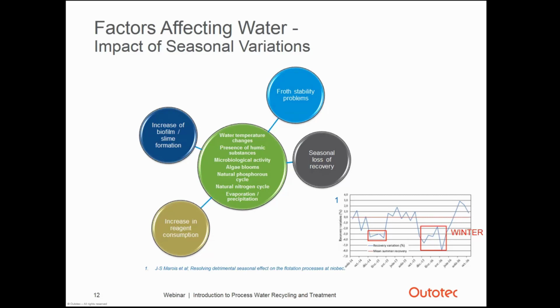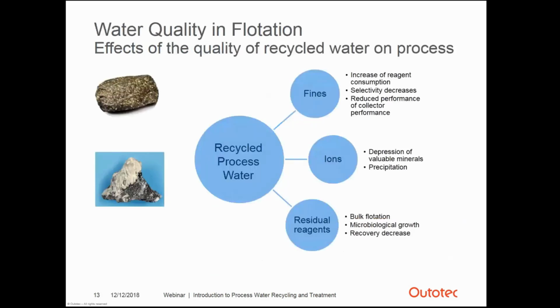There are several components that can be accumulated in recycled process water and therefore harm the flotation performance. Here are the most critical ones: fines, ions, and residual reagents presented in these blue bubbles. Firstly, fines. And when we are talking about fines, we consider under 20 micron size of silicates, talc, clay, organic material.